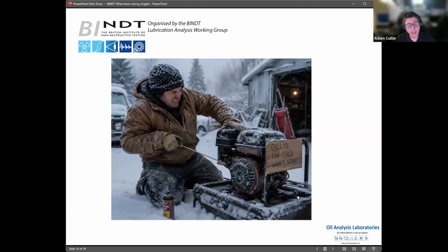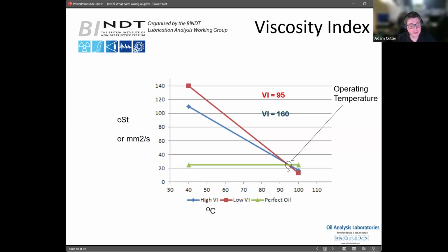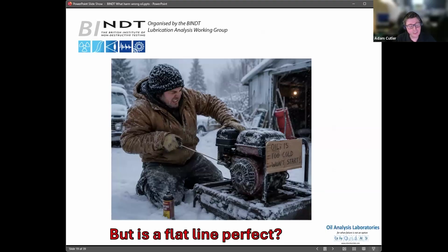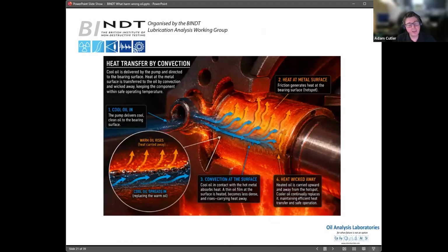So who will this suit? Someone who's working in these cold conditions here, they're trying to start the engine. They want this to be as close to this perfect line here because they want it to not get too thick when they're at colder temperatures. But this doesn't necessarily suit everyone. So if we take an oil that is being used to transfer heat away from a component, you actually want that as soon as it heats up to get very thin very fast so it can flow away to allow fresh cool oil to go and cool down the component. So a very low viscosity index would be desirable in those circumstances as opposed to the high viscosity index when you want good temperature stability.